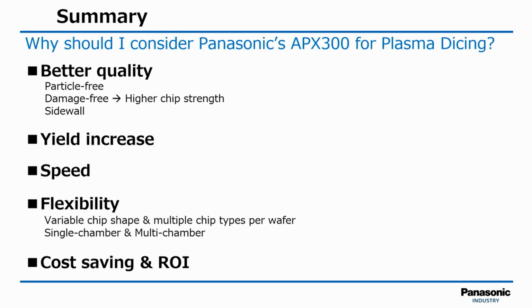Speed can be greatly increased, so this definitely also helps with your return on investment. The wafer is diced in one hit, so it depends on the thickness of the wafer. If we can achieve thinner wafer thickness, speed can be increased. Flexibility is also very high with plasma dicing, so you can decide the layout of the wafer, and as I said, if you have large sensors which are not square, these are possible. And yes, all of these things put together basically lead to cost savings and a very good ROI.